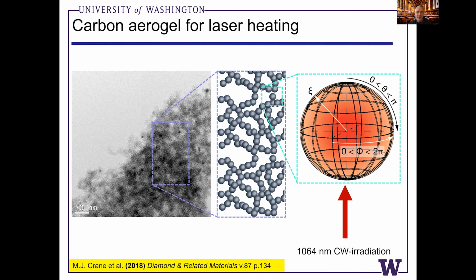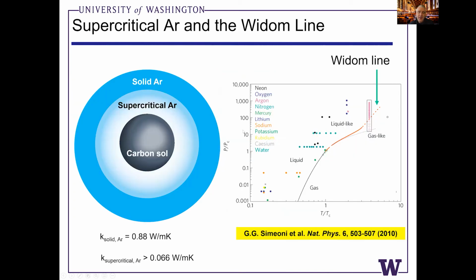It's still very dense, but it would have a fluid-like, supercritical character and have a much lower thermal conductivity. So the idea was we could potentially melt the solid crystal to make a supercritical argon insulator around the carbon material. If you compare, we did our best to find the thermal conductivities of these materials. Fortunately for argon, there's a lot of great literature that's been measured, and the thermal conductivity of solid argon at around 20 gigapascals is just under a watt per meter Kelvin.